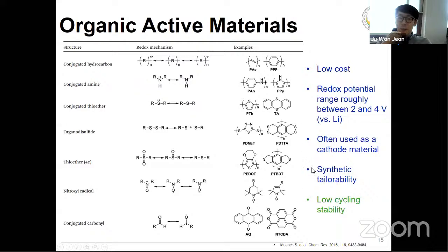It has a lot of advantages such as low cost, and its redox potential range is roughly between 2 to 4 volt, which means it can be used as a cathode. And some of the organic electroactive materials can also be used as an anode. And synthetic tailorability is also a big one: by introducing the pendant group or by controlling the molecular structure of the polymer backbone, we can control the redox potential.